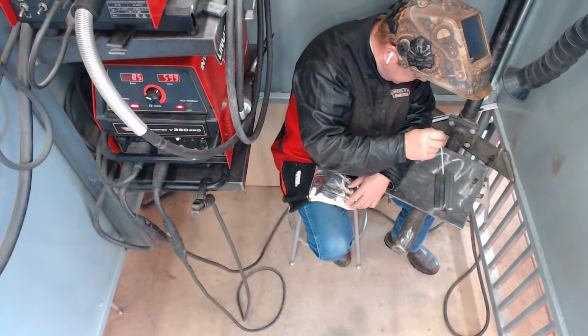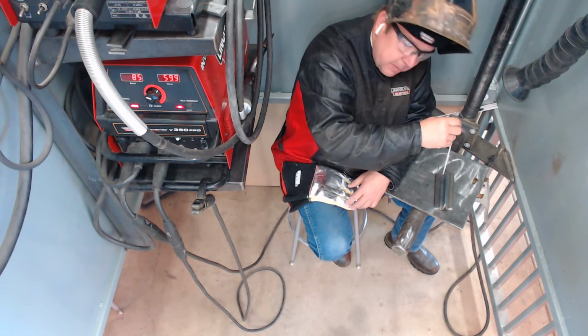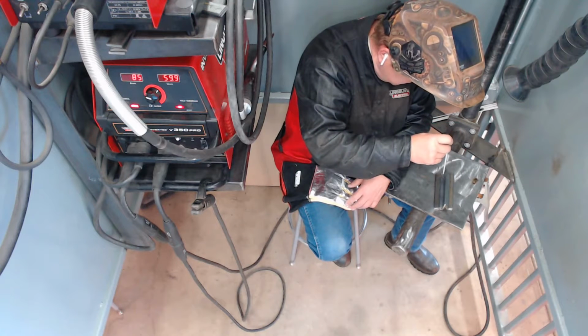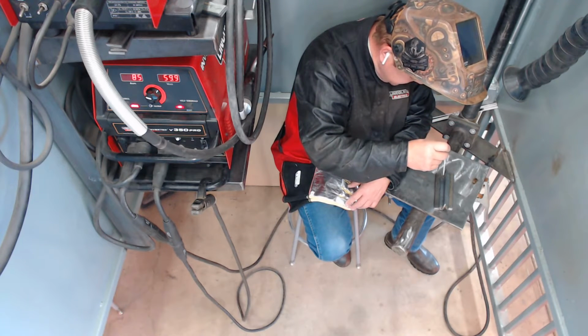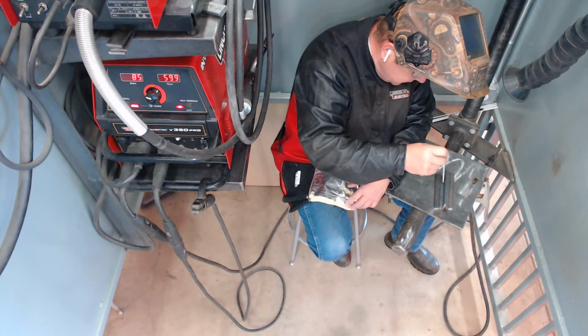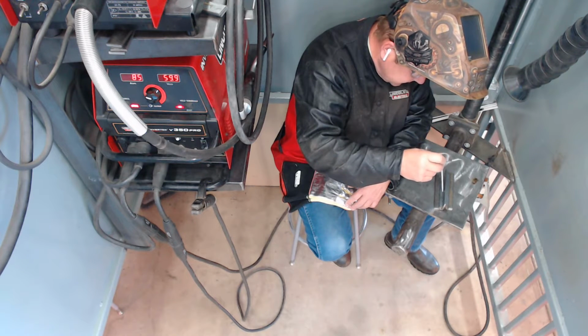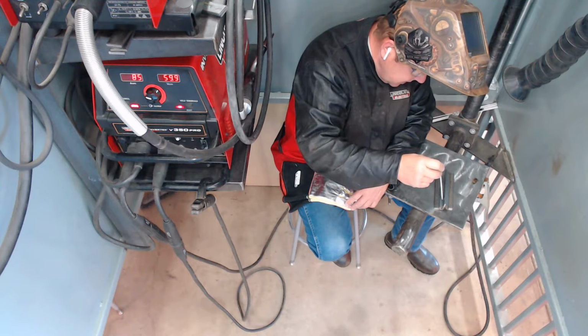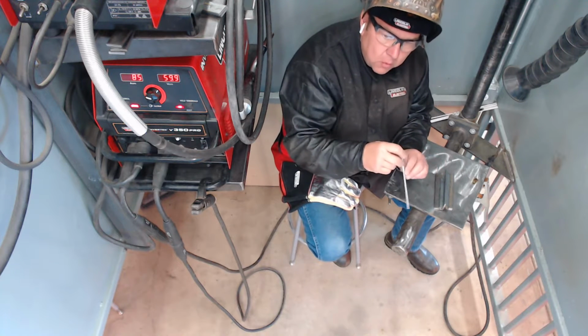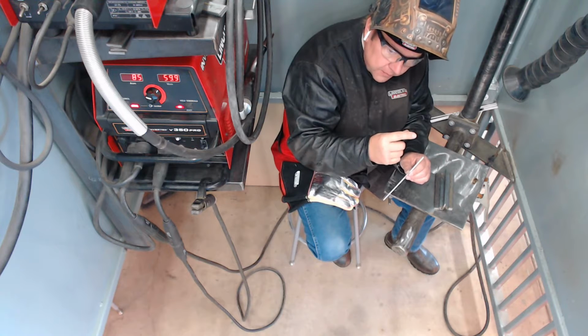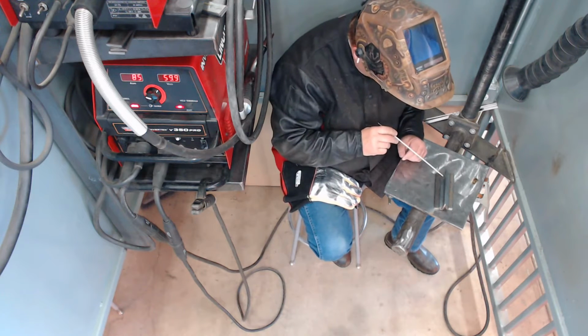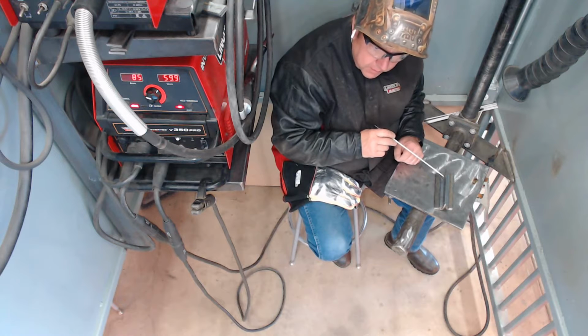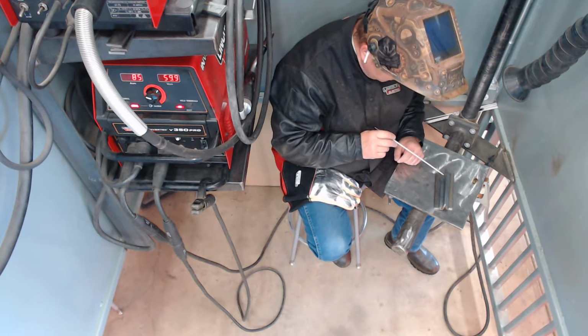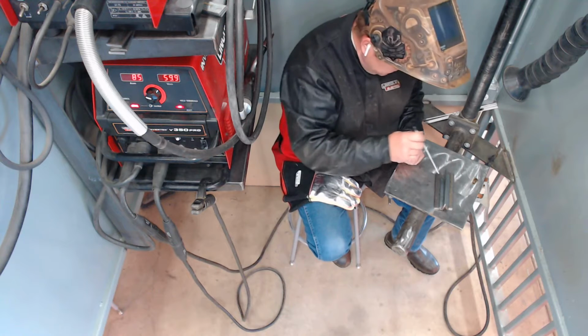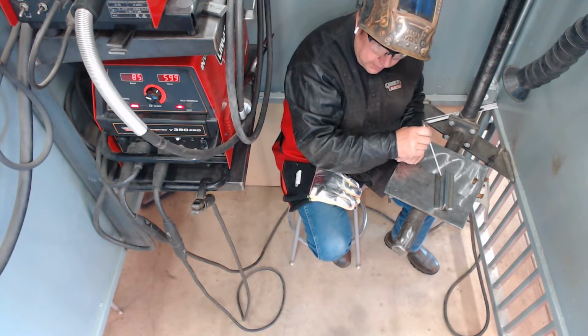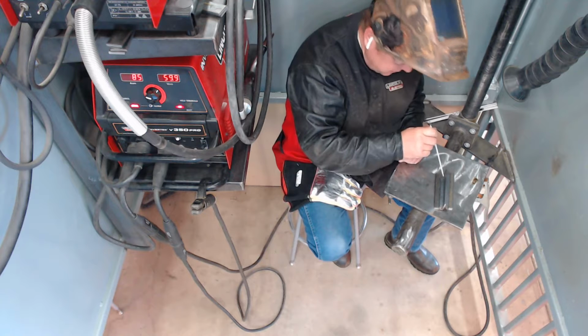All right? So you're going to strike your arc. Your electrode's going to be in about this position, and then you're just going to drag it slowly as you move it in this direction. As you are moving in this direction, you will watch what we call the weld puddle as it washes up onto this crack right here where the pieces of metal meet. If you can't see that weld puddle washing up onto that crack, then you're too far out this way, and you need to move your electrode in a little closer.